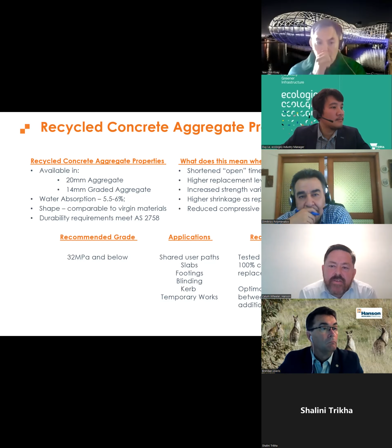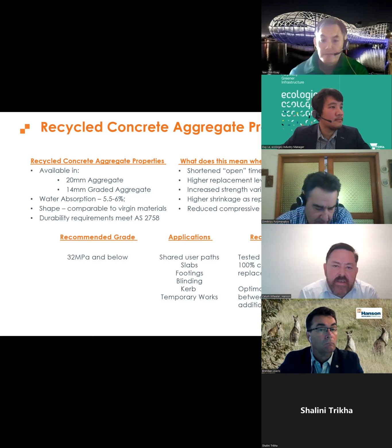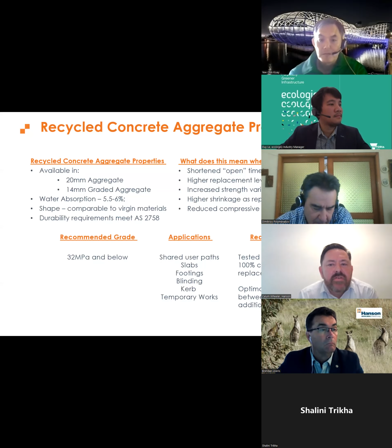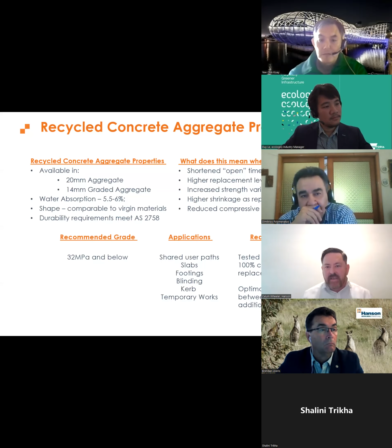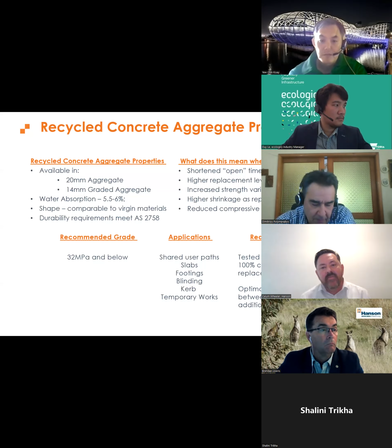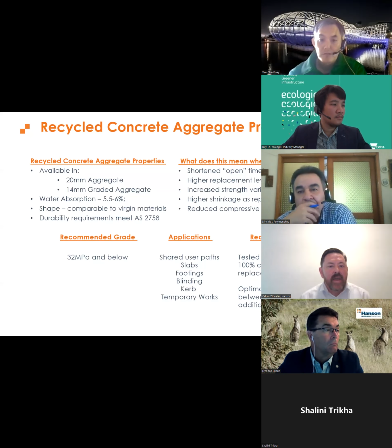What about when we put it into the ready mixed concrete itself? What we found when we started doing the trials is that it can shorten its open life or its plastic properties. At heightened replacement levels, it will lower the bleed properties of the mixes, and is also likely to increase the variability of strength results. Also at higher replacement levels, we saw an impact on shrinkage results and ultimately some reductions in compressive strengths by pushing those replacement levels so high.